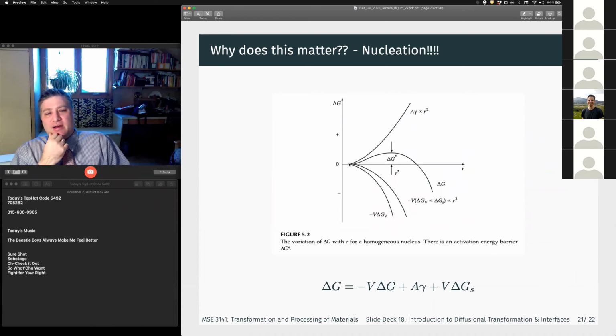So before, in liquids, we only had our bulk free energy, and we had a surface effect. And now we have to add in another effect, which is the coherency strain, which is going to reduce our driving force. Since we have to pay an energy penalty to create those coherency strains, we're going to reduce our bulk driving force, which is going to shift our critical radius out to higher values, and our Gibbs free energy activation hump to a larger penalty. Which means it's going to be harder to nucleate. If we have a bigger activation energy and a larger R star, we're going to have more difficulty nucleating.